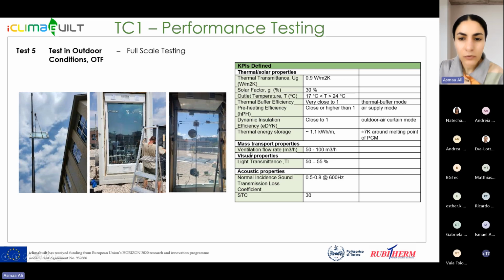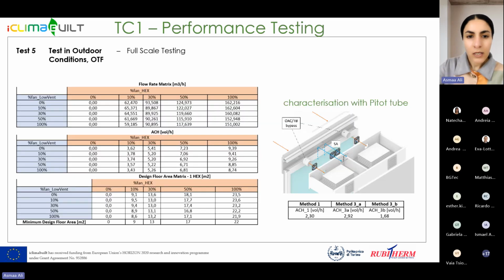So the ventilation flow rate was also defined between 50 to 100 cubic meters per hour, and light transmittance between 50 to 55%. And finally, we will have acoustic KPIs. So to verify these KPIs, first, ventilation flow rate was tested in an outdoor test facility.